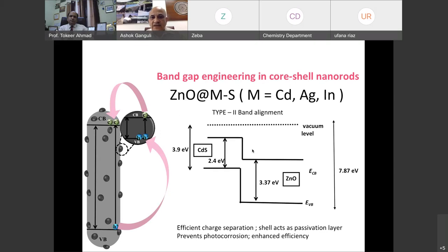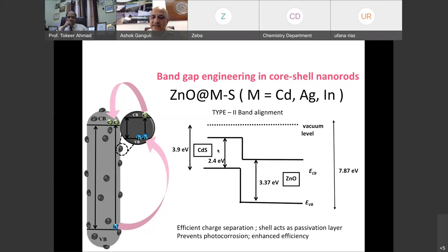This is our first example — a very celebrated, highly cited paper. We made zinc oxide, which is a UV catalyst, and converted it into a visible catalyst by making a shell. We combined a high band gap material, zinc oxide at 3.37 eV, with a mid band gap semiconductor, cadmium sulfide at 2.4 eV. This is a type-2 semiconductor geometry where the conduction band of one is higher than the other. In this type-2 geometry, visible photons are captured by cadmium sulfide, which acts as a sensitizer and then transfers electrons to zinc oxide, while holes are separated on cadmium sulfide.